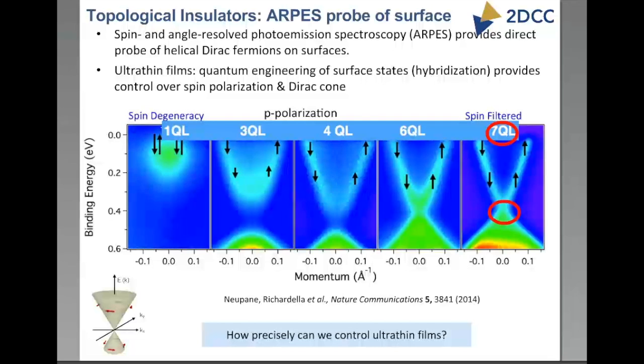I've shown you these AFM images where you have textured surfaces. So what does it mean to have a 3 quintuple layer film? When someone is doing ARPES, this was our collaborator Zahid Hasan at Princeton and his students who took this data. But what does it mean when you take a 100 micron spot for an ARPES measurement and you measure this very clean spectrum, and at the same time you have all these stepped surfaces? So these are important questions that we need to understand, and certainly we want to be able to grow really, really ultra-flat films.